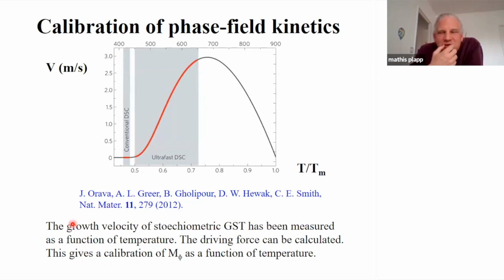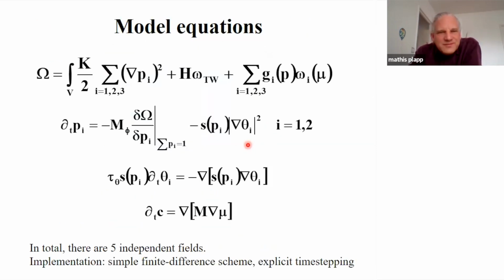Okay, and then we also had to calibrate the phase field mobility. This is always a difficult subject, but here we had some data on the crystallization speed of pure GST, which were published in this very nice paper. It has the characteristic bell-shaped curve. Here, the crystallization speed increases because the driving force goes up. And then here it goes down again because the mobility of the atoms goes drastically down as we are approaching the glass temperature. So we have sampled these data and used this to express our phase field mobility as a function of temperature.